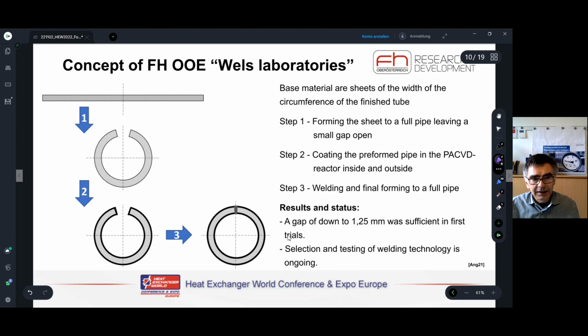Our approach was different to that of the Braunschweig institutes. We take a strip of steel and form it to a tube with a gap. You can also use a standard tube and make the gap inside again. So this is what the industrial way would be for the time. Then we coat this tube with the gap inside and outside with DLC. And then we do the welding and have a tube with inside DLC coating again.